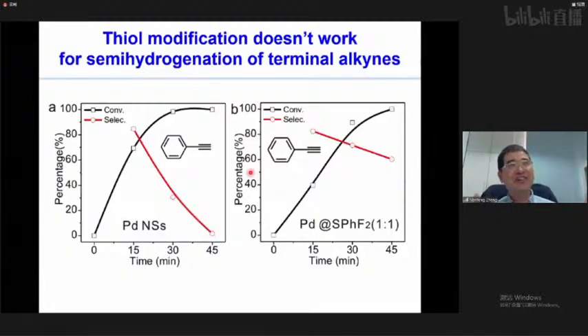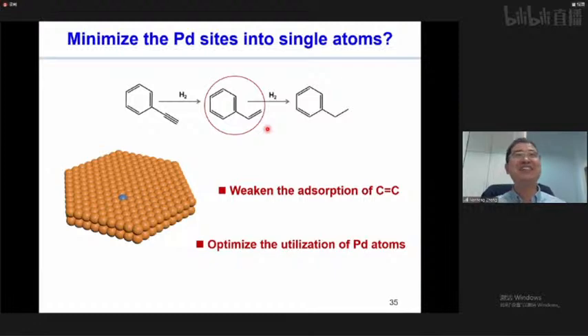However, the steric hindrance from the thiolate modification is not big enough for terminal alkynes, because this alkyne can easily interact with the palladium surface, even with small space. So how can we solve this issue? We considered that if we could minimize the palladium size into single atoms, we should be able to resolve this issue, right? Because the bonding of this alkyne to a single atom of palladium should get weakened.